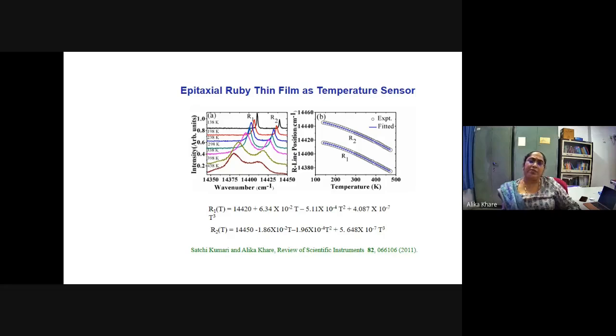The advantage with this kind of photonic temperature sensor is that they are immune to noisy environments. Since these are dielectrics, they are not sensitive to magnetic fields or RF noise, so one can use them in any environment. The temperature range is also very high, because the melting point for ruby is extremely high - more than 1000 Kelvin if I recall correctly - and it can go to very low temperatures also. It is also in a very miniature form, which is another advantage - a very light photonic sensor.